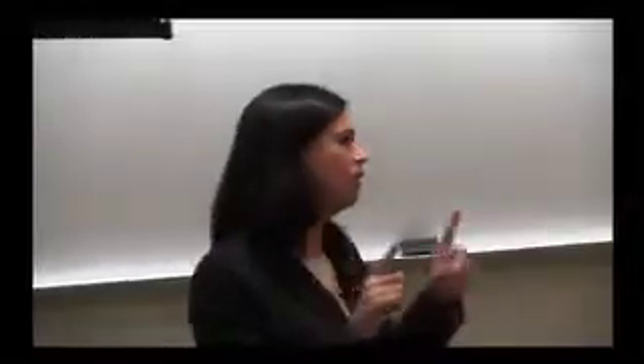So if you have these four under control, you will get really nice working digital circuits from printed electronics. If you have threshold voltage shift by stress, it's not going to work. If you have bad printing, where one channel is 20 microns, the other is 25, the other is 30, once you put it in a ring oscillator, the ring oscillator doesn't work.